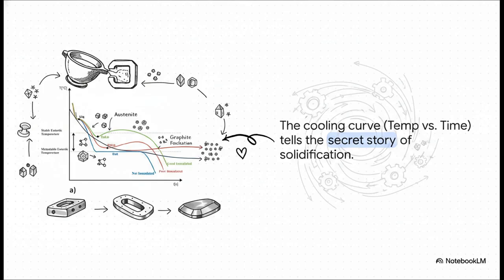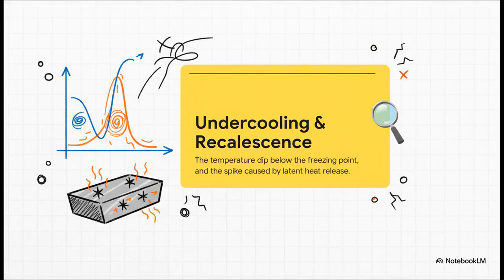Every little dip, every plateau, every single rise on this curve, it all corresponds to a specific event, like austenite forming or graphite nucleating. The shape of this curve tells the whole story. There are two key things we're looking for here: undercooling and recalescence. Undercooling is that first dip below the actual freezing point. It tells us how much of a kick the metal needed before it would finally start to solidify.